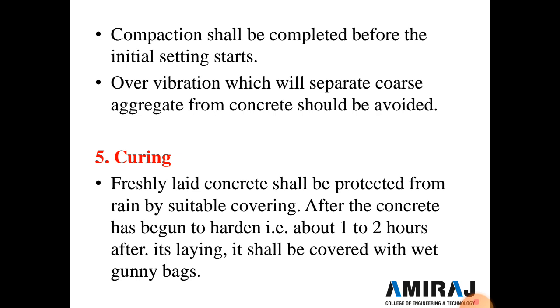Now the fifth and important point of the concrete is curing. Freshly laid concrete shall be protected from the rain by a suitable covering. This point is valid when the concreting is done in a rainy season. So in a rainy season, freshly laid concrete shall be protected by a suitable cover, like plastic sheets, and after the concrete has hardened, about 1 to 2 hours after its laying, it shall be covered with wet gunny bags. Wet gunny bags or jute bags are generally used for curing purposes.